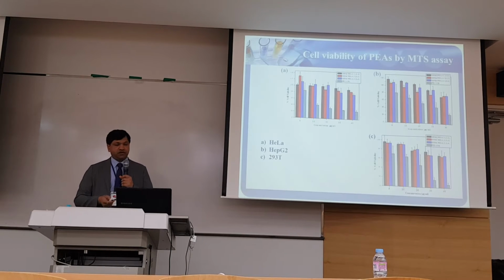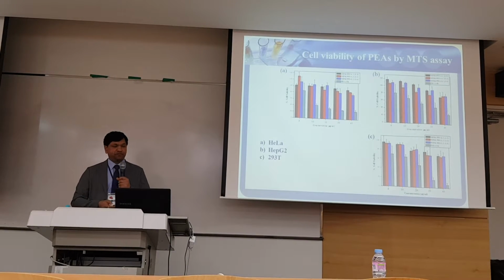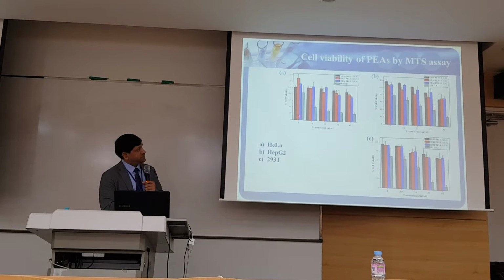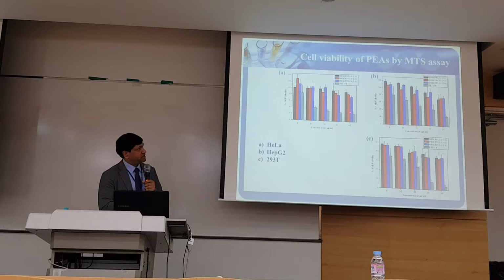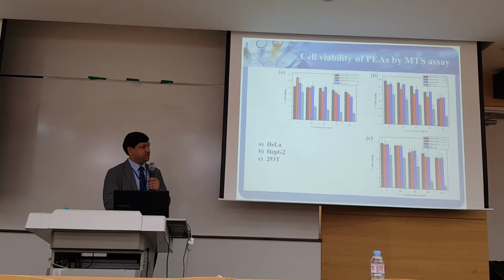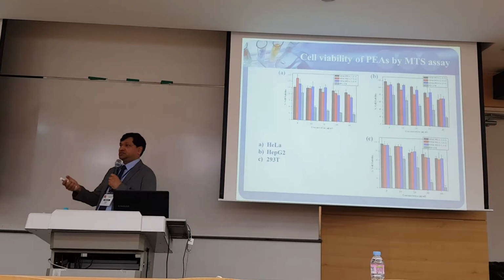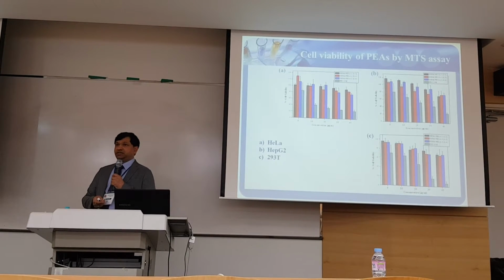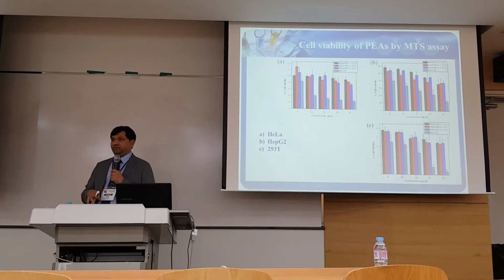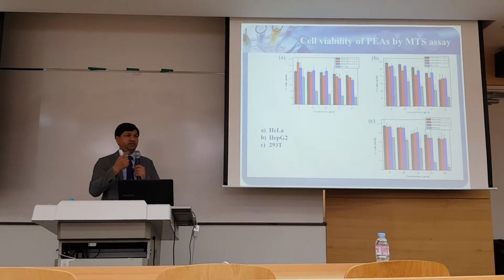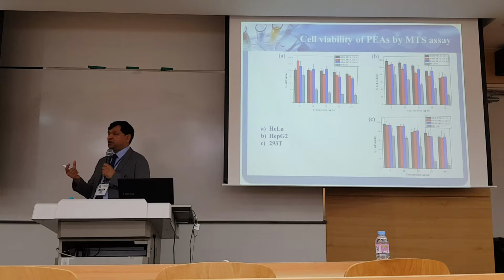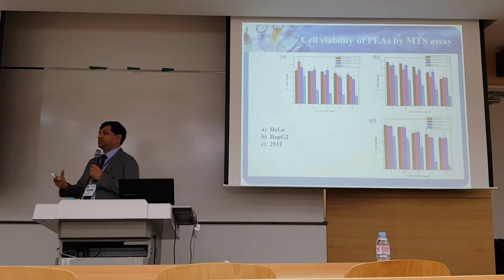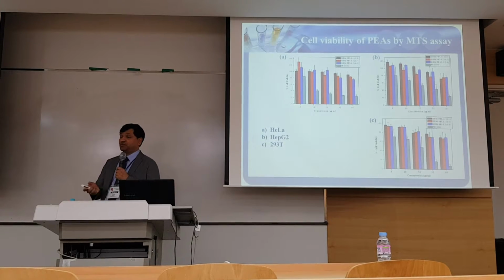So we decided to apply it for further toxicity studies. In different cell lines, HeLa, HepG2 or even 293 cells, compared to the green bar of the PEI 25K, it shows very high cell viability, indicating that the presence of ester linkage in the backbone leads to hydrolysis in the cytosol, and thereby there is no toxicity. Because generally toxicity arises from the deposition of these kinds of non-biodegradable materials for a longer time in the cell, and ultimately it comes in contact with different serum proteins as well as different cellular proteins.